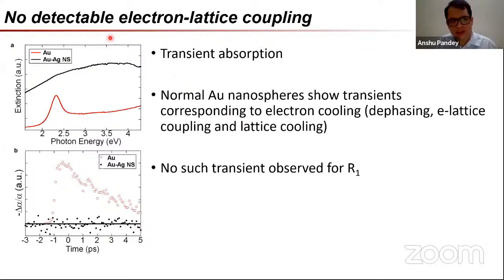It gets stranger, because if we look at the electron lattice coupling, which is measured via transient absorption, for a normal gold nanosphere, if you pump it, you find that there's actually extensive electron lattice coupling. There are dephasing events, there's electron lattice coupling which follows that, and finally lattice cooling, which all show up in transient spectroscopy. In the case of AuAg, there is no such transient being observed.